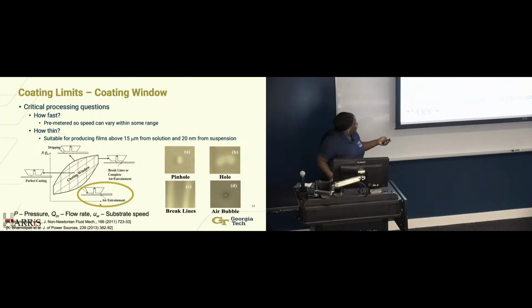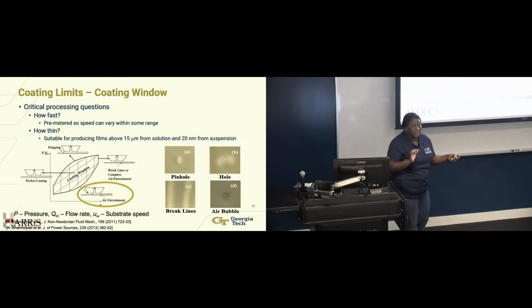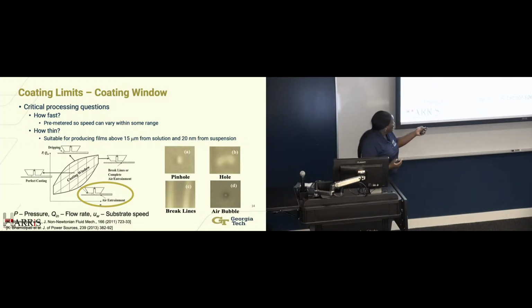From a commercialization standpoint or industry standpoint, this is the line that they care about, that low flow limit. Why? Because this is controlling how fast I can make the material with said quality. This line here can technically be pushed out some. Why? Because it's based on defects that affect the performance of the device. So some devices may be okay having a few air bubbles entrained because I'm not compressing it and there's no crossing of gases or what have you. Whereas others, if I go past this point, then I would have a problem. And so we're trying to figure out what's that boundary for a variety of different materials.